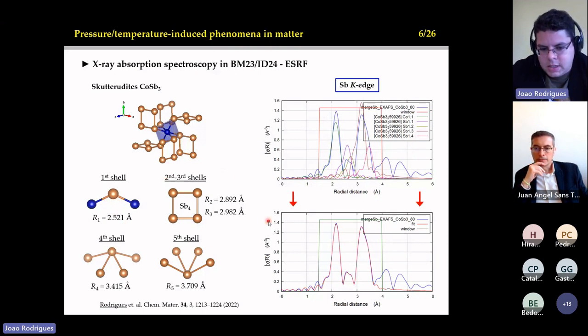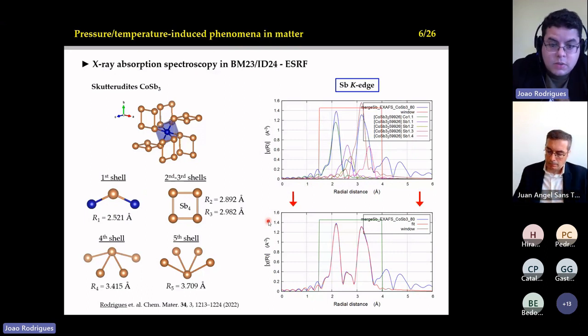So my work was basically to combine X-ray absorption, which is a local technique. Okay, this is an important factor. Combining the local technique with the long-range order technique, which in our case was X-ray diffraction.